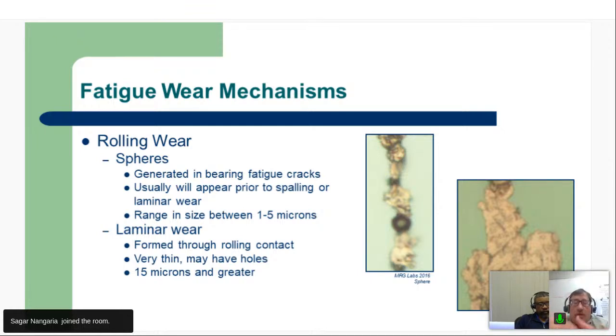And sometimes they'll show up early in the process, maybe even before you see the spalling or laminar wear, but very, very small spheres. But then we get into the larger laminar wear particles, where these are just coming up off of that surface due to the subsurface cracks that have formed. And they may be so thin you can see right through them in spots, right? Yeah. You can see that.